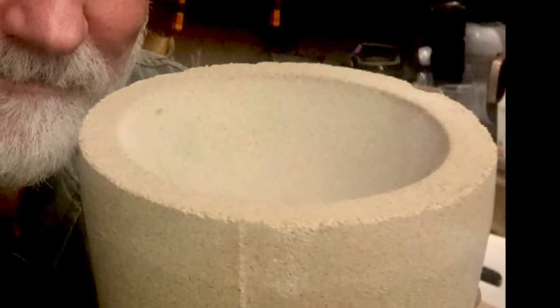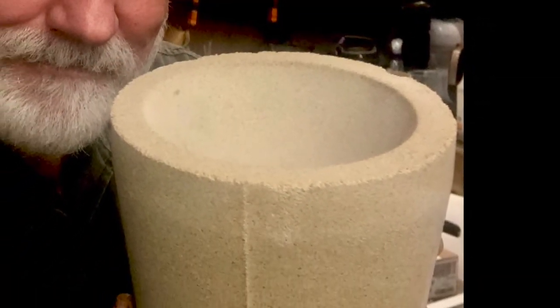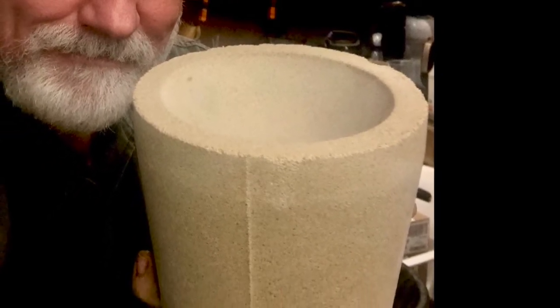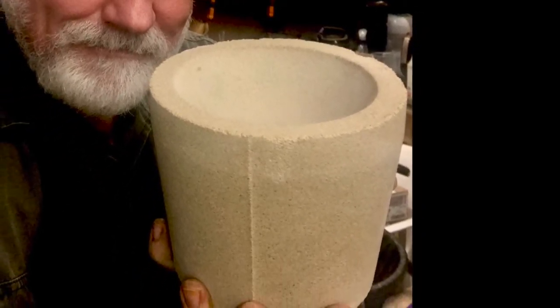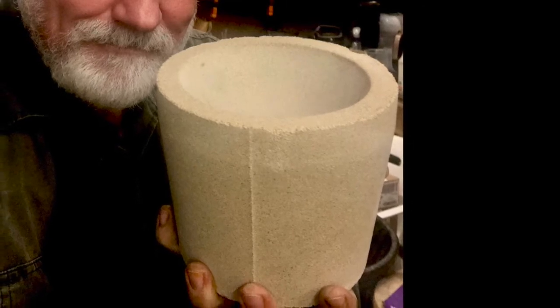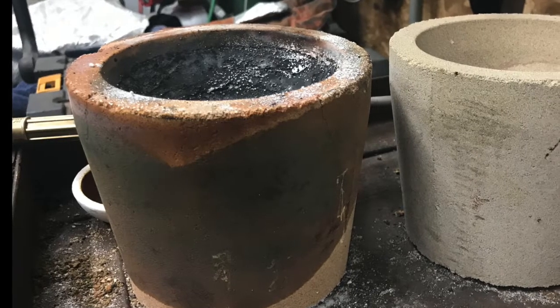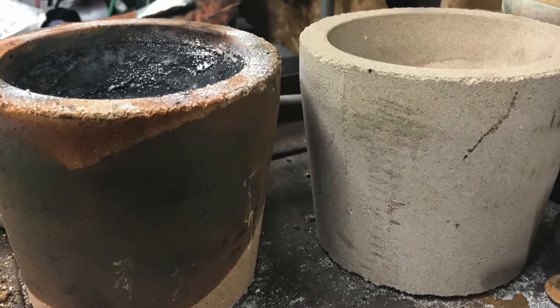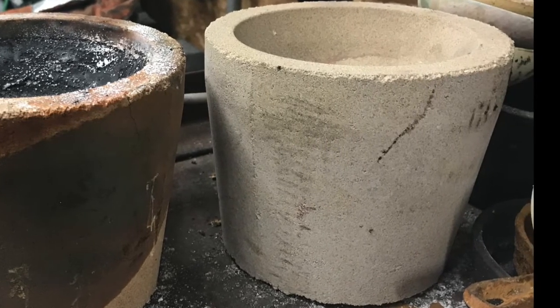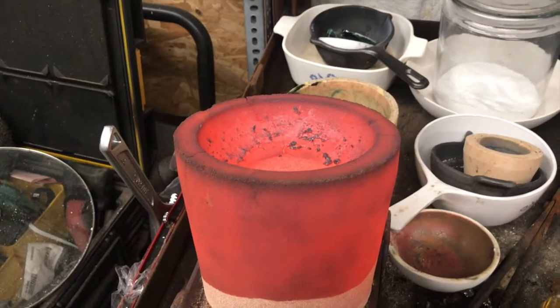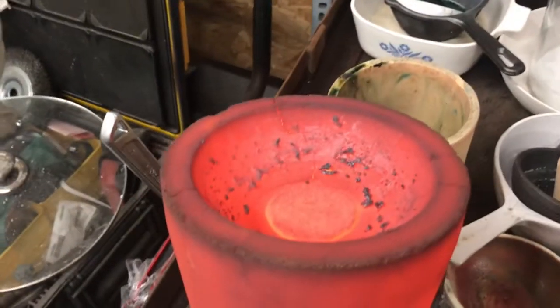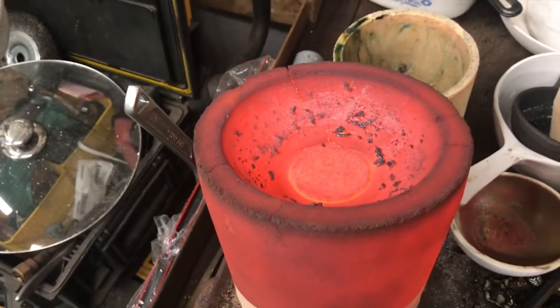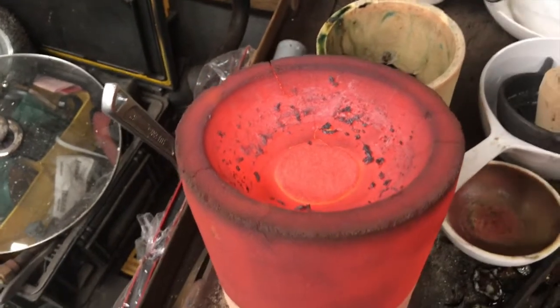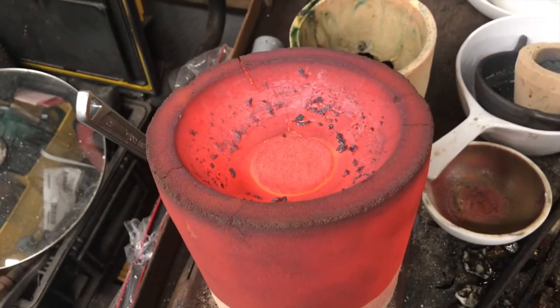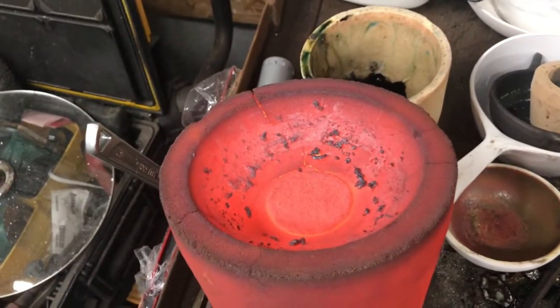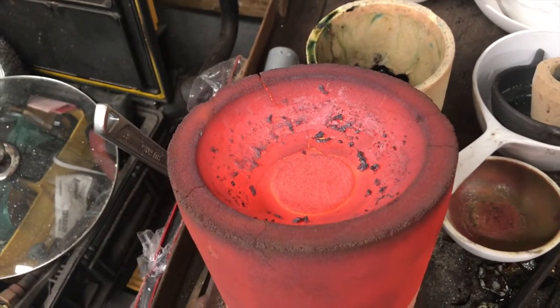This is more of a production size, which would fit in that oven and do a decent amount of lead gold alloy at once. The one on the left is used, it's absorbed the lead. The one on the right is new, to show you the difference. This one just came out of the oven and it's red hot, and the precious metal disc or round is in the bottom there. It hasn't been popped out yet, so it's still glowing.